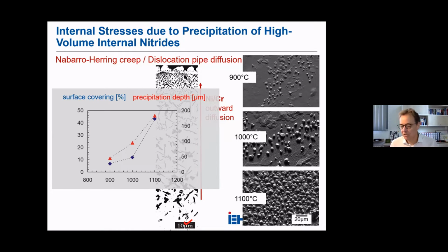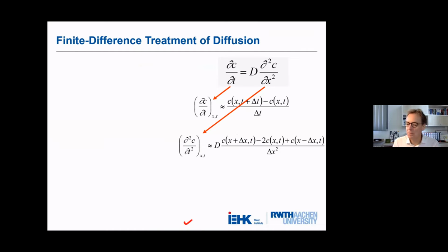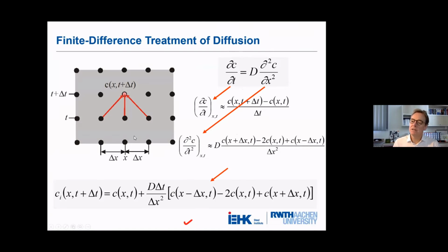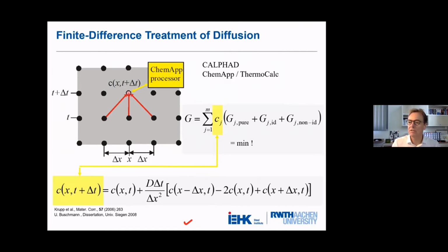To account for this kind of effect, we tried to solve the Wagner or the underlying diffusion equations numerically by means of finite differences. Here the differentials of Fick's second law are replaced by difference quotients. Basically, that means we have three concentrations at a time step t, and using these three concentrations we can calculate the concentration of the following time step by this difference equation. That is pretty simple, but we have to consider the precipitation process, that means the thermodynamics.